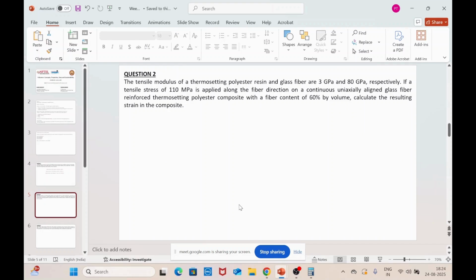So it states that the tensile modulus of a thermosetting polyester resin and a glass fiber is 3 gigapascal and 80 gigapascal respectively. Again, here also if you see, the modulus of the reinforcement is greater compared to your matrix. If a tensile stress of 110 megapascal is applied along the fiber direction on a continuous uniaxial aligned glass fiber reinforced thermosetting polyester composite with a fiber content of 60% by volume, calculate the resulting strain in the composite. So here you are given the tensile modulus of both the matrix and the filler.